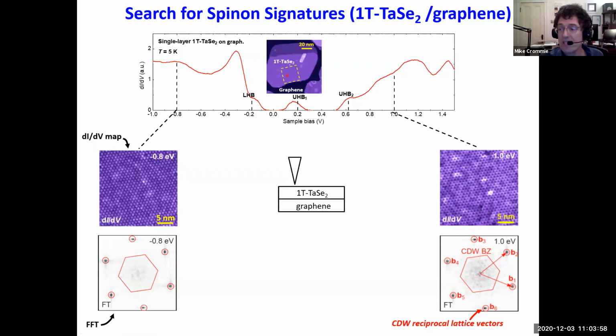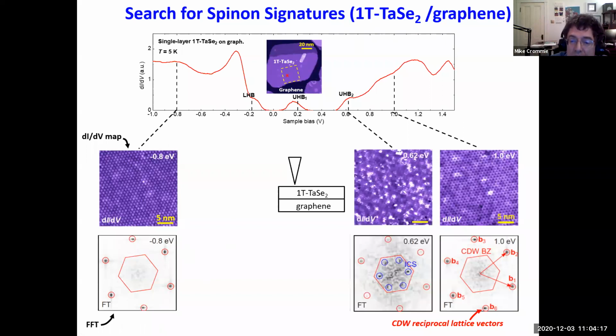And if you take a Fourier transform of these images, then you really get nice peaks here at the reciprocal lattice vectors of the CDW. So that's the only real well-defined periodicity that we see. But now let's look at energies closer to the Hubbard band. So let's move into the Hubbard band. And when we do that, let's first go to this part right here, what I call UHB2, the upper Hubbard band, the higher energy part of the upper Hubbard band.